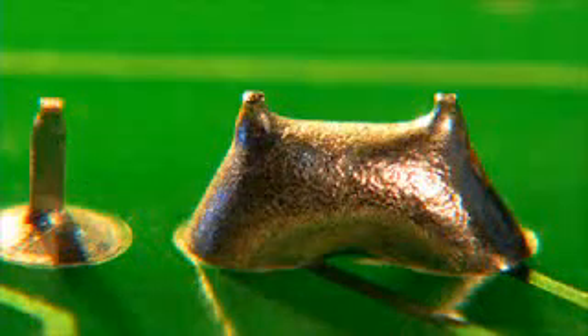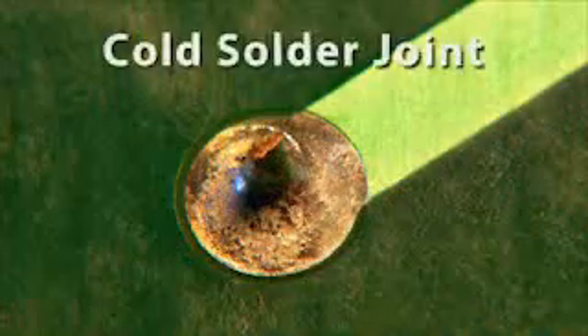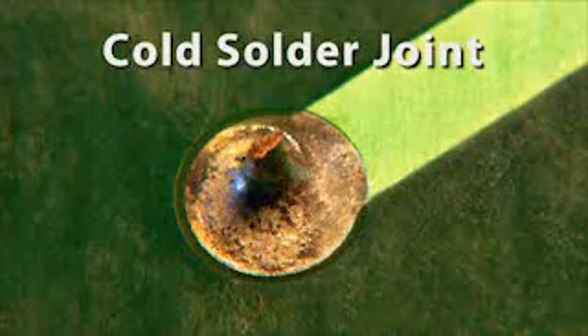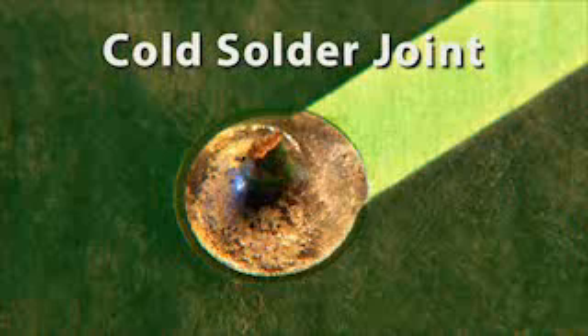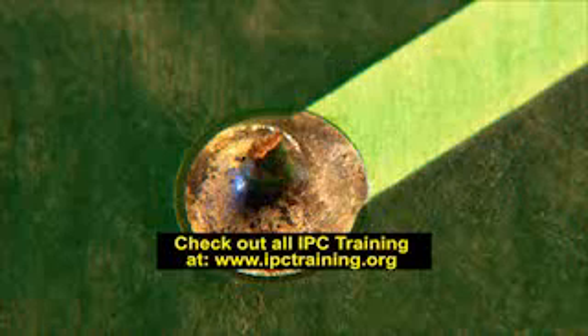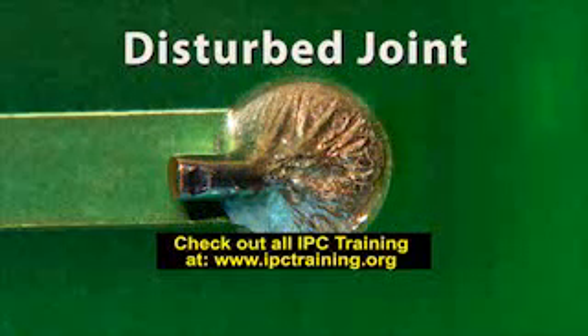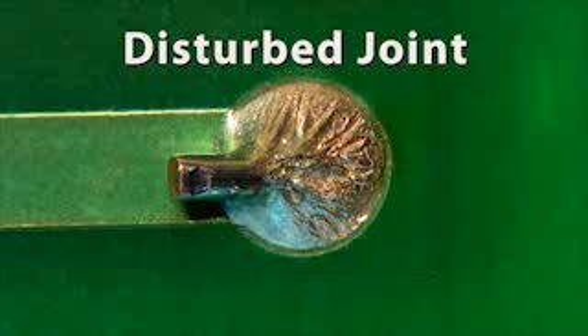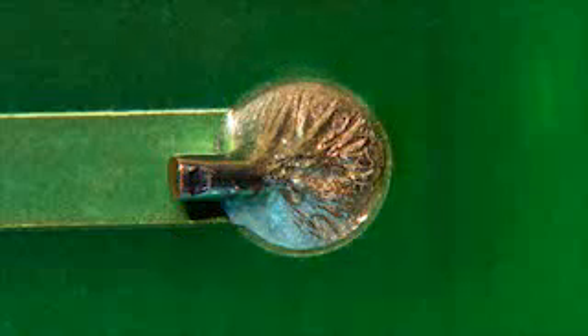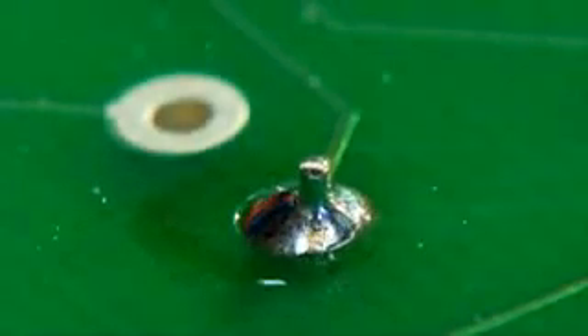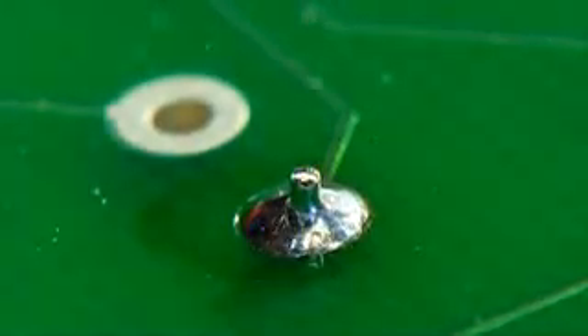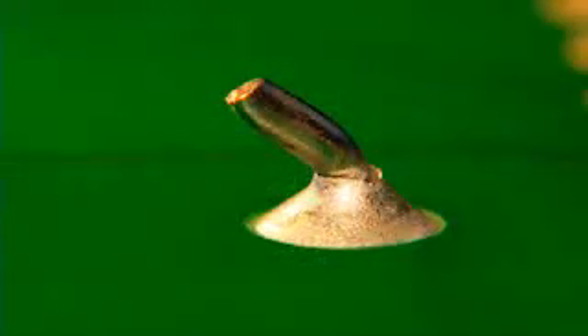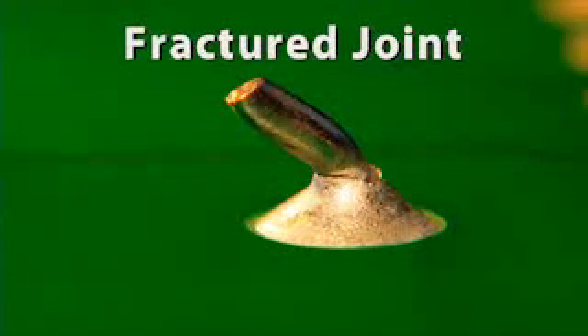Now let's look at some solder joints that are considerably less than ideal. This is a cold solder joint. Notice that the surface of the solder is dull and grainy. This is usually caused by insufficient heat. This is a disturbed joint. You can see that the solder shows stress lines, similar to the foothills in a mountain range. Movement during the cooling process can cause this condition. This is a fractured joint. The lead may have been moved after the solder solidified.